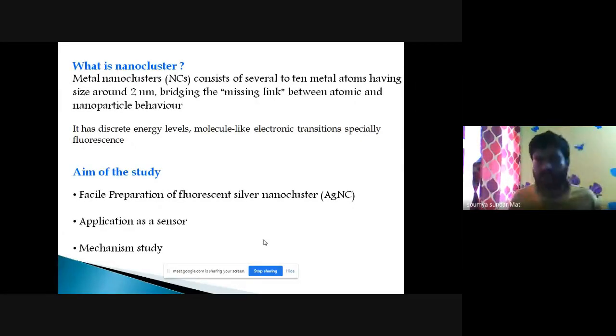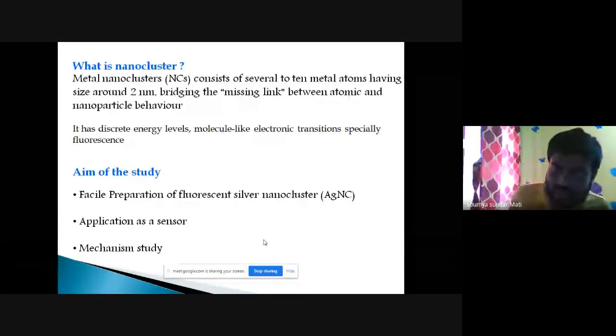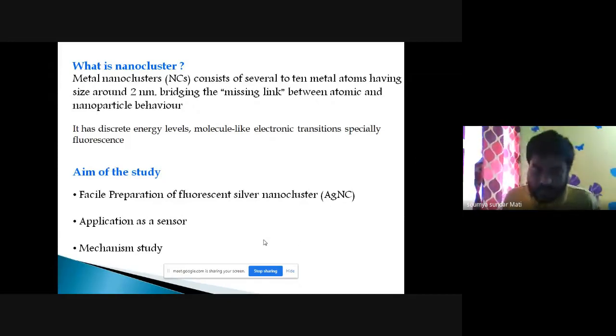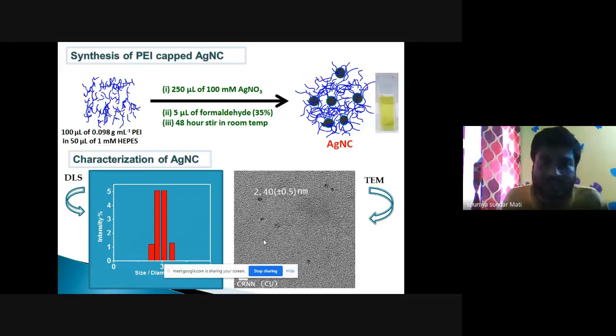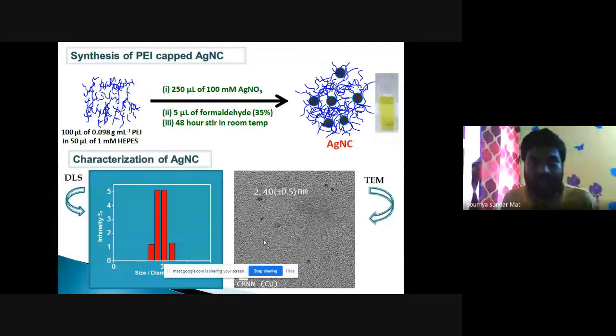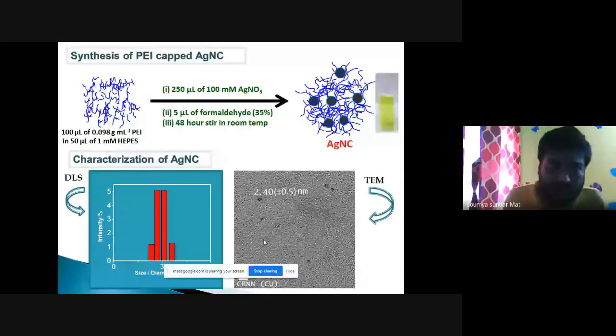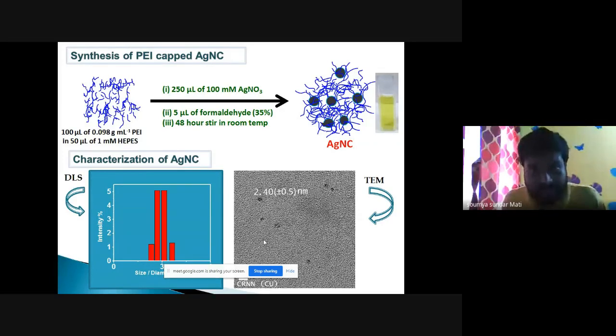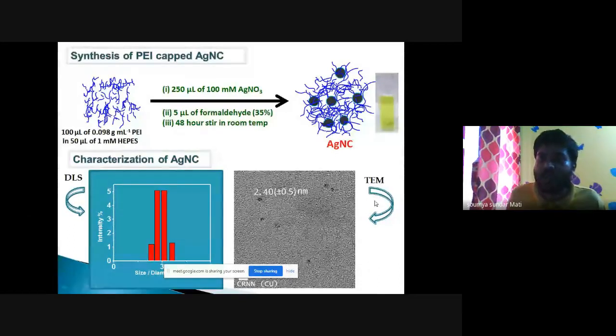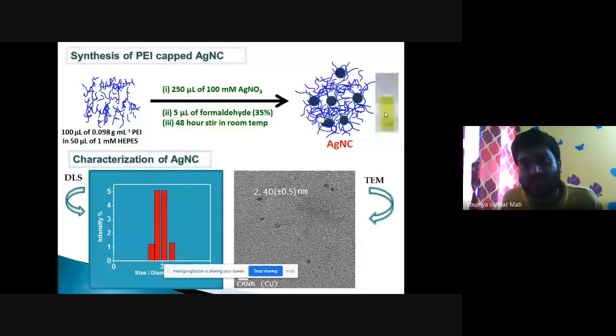Now, the aim of our study is mainly threefold. First, facile preparation of fluorescent silver nanocluster. Secondly, application of these fluorescent nanoclusters as a sensor. And third, the mechanistic study of this sensing behavior. First, the synthesis of silver nanocluster stabilized by polyethylene imine, that is PEI. We dissolve the PEI in aqueous HEPES buffer medium at pH 7, followed by adding silver nitrate and the reducing agent formaldehyde, and it is stirred for 48 hours at room temperature. After that, a pale yellow solution of silver nanocluster stabilized by polyethylene imine is generated.